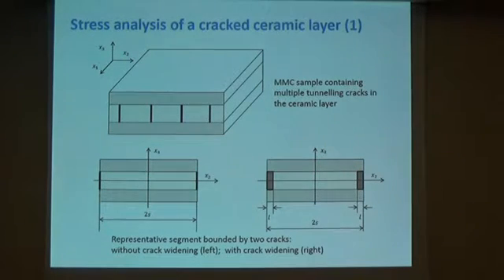And we started with looking at this simple configuration, a ceramic layer between two metal layers. And the ceramic layer contains a number of cracks transverse to the plane of the laminate. So we assume for modeling purposes that cracks are spaced uniformly and that they span the whole width of this sample. And because of that, we are able to model a representative segment of the sample bounded by two cracks, as shown here on the left. So these are cracks without crack widening, and this is a sample containing two cracks with crack widening. So cracks are actually like rectangular holes in the sample.